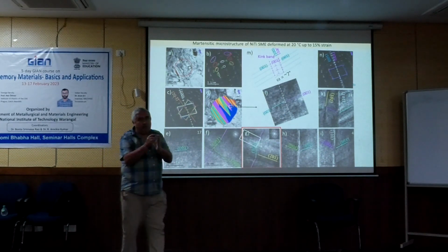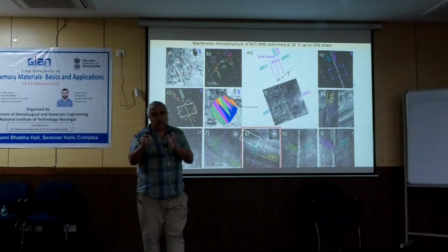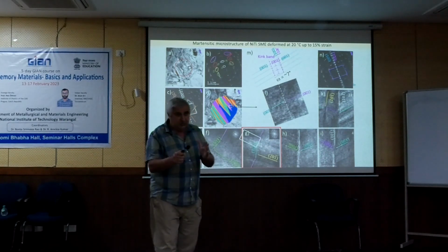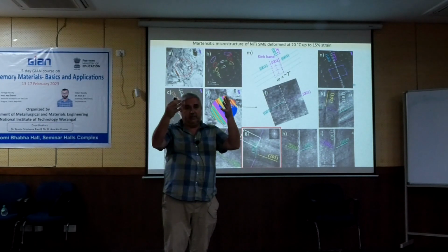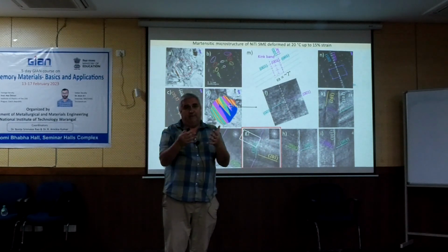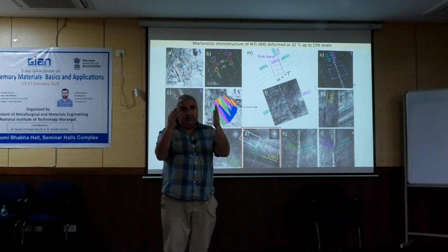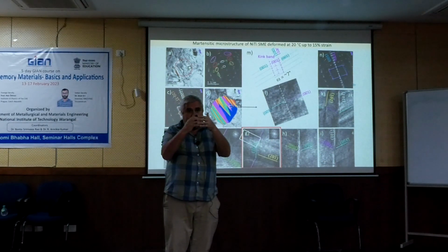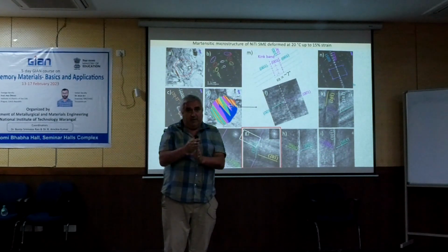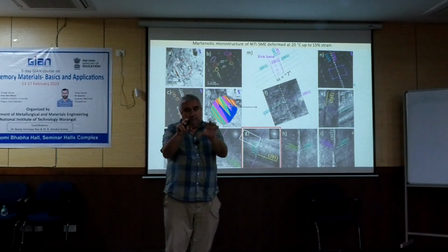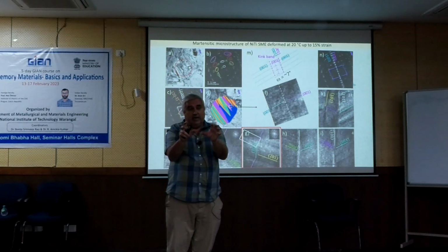There is no meaning to compare it with low angle grain boundary, because low angle boundary concerns a single interface which is created during the growth of the crystal, for example. So you have a crystal with many dislocations, aluminum, you heat it, and these dislocations annihilate, and they create a low energy grain boundary because the energy is minimized. So lattices are rotated across the low energy grain boundary and it's coherent.